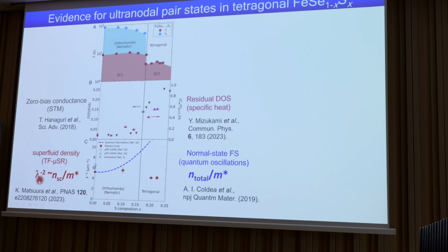μSR allows us to measure the absolute value of the superfluid density, which is 1 over lambda squared. Lambda is the penetration depth. This is a measure of the superconducting carrier density divided by effective mass, plotted by these red dots. That quantity can be compared with the normal state carrier density divided by m star, estimated from quantum oscillation measurements. Because we use very high quality single crystals, we can observe the quantum oscillations, which can be estimated by this dashed line.